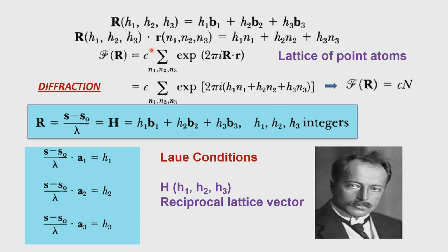We showed some points which come out from the scattering experiment. Whenever scattering experiments are done on crystalline objects, if it is a 3-dimensional crystal, we will get spots, and these spots represent the values of H1, H2, H3, that is, where the spot will occur with respect to the reciprocal lattice. So we can find the coordinates of the reciprocal lattice point in terms of H1, H2, H3, which can be replaced later by HKL, the so-called Miller indices. This is where Laue completed this work, and he got the Nobel Prize in 1914, I think.